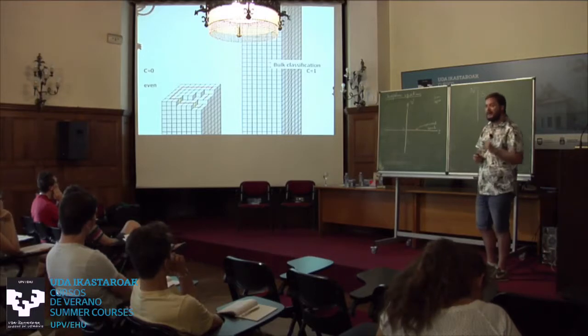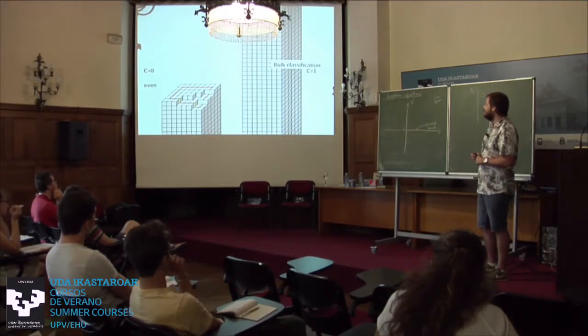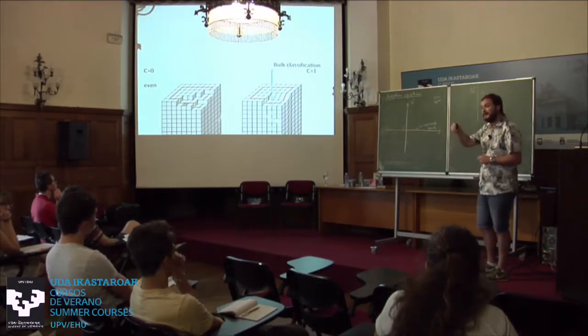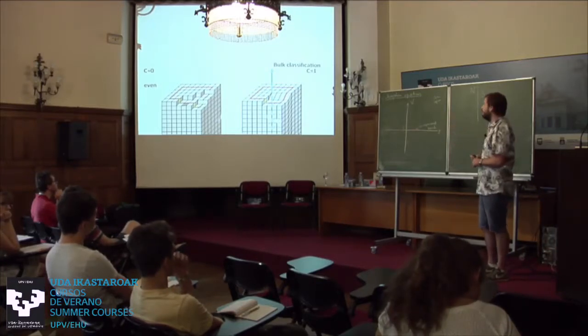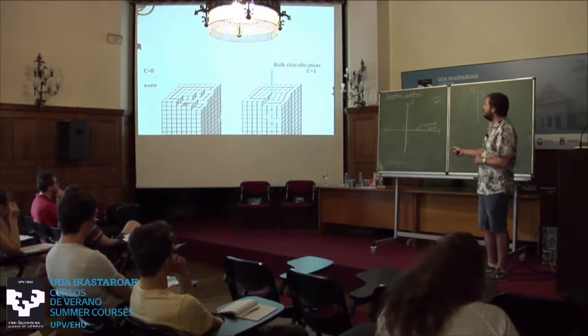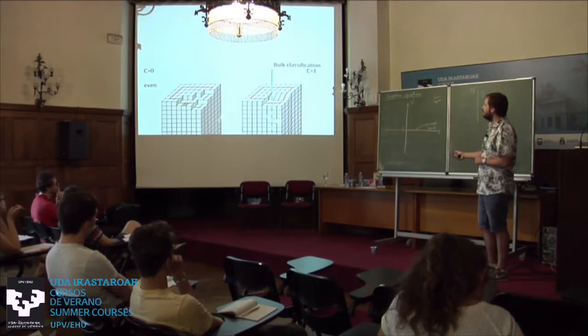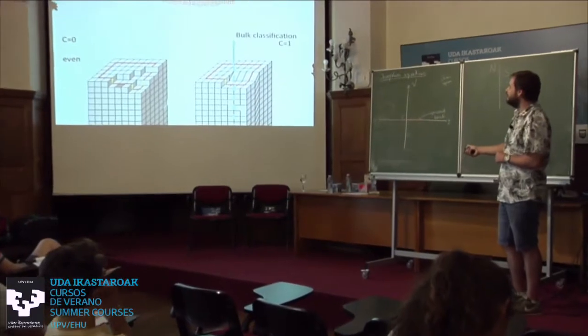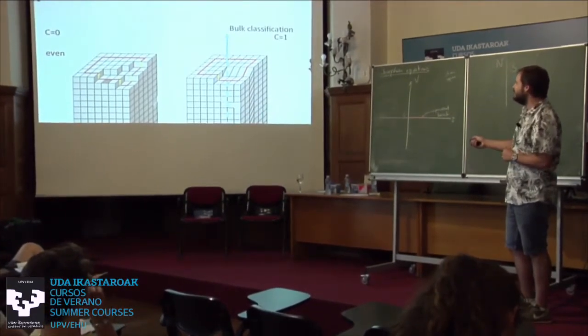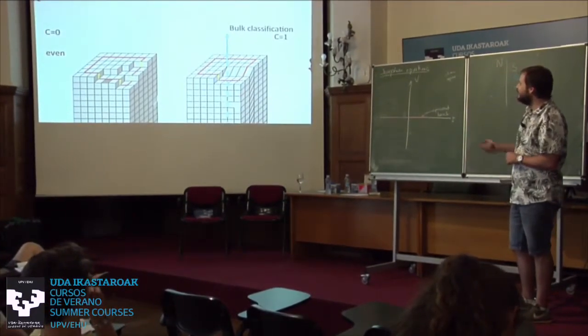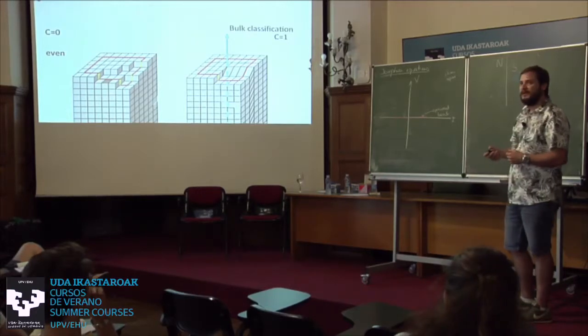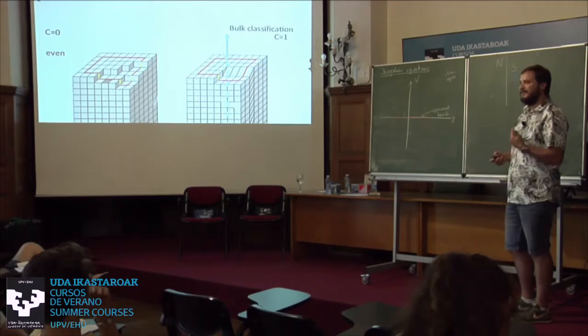The one way to get an odd number of crossings is to have a screw dislocation terminating inside the contour on that surface. Here is the termination of a bulk material with a screw dislocation — you can see the displacement. If you go around on the surface, you cross a single step edge.